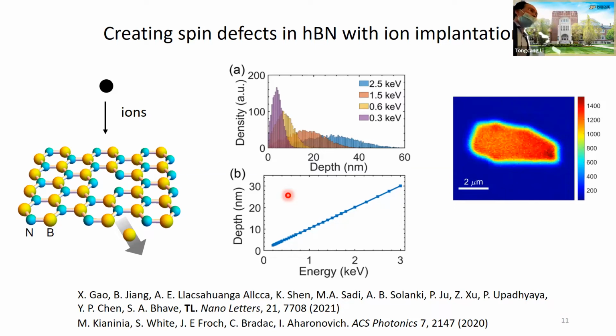And of course, if you want to create defects locally, one way is to use some mask, like a photoresist with some holes. Then we can implant the hBN with these ions. This is just one example. We show it's quite homogeneous, but we also have larger samples. We just directly put the flake on a silicon wafer, and the resolution is on the order of 1 micron.